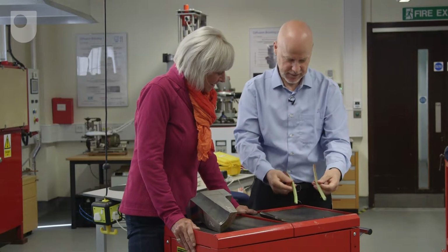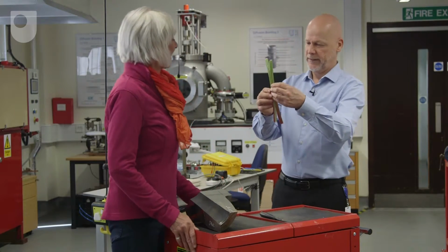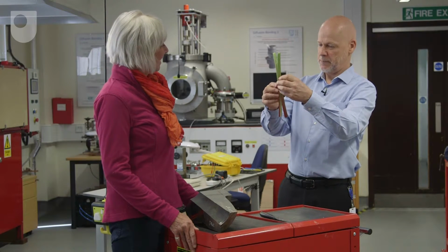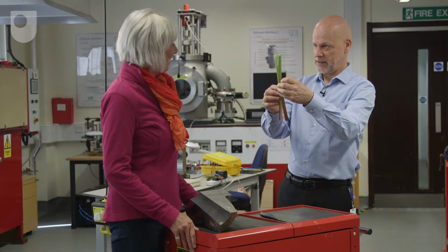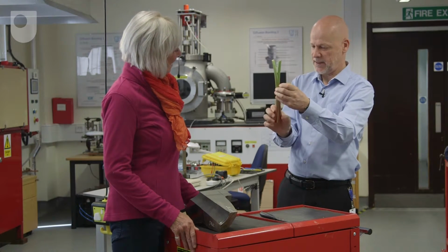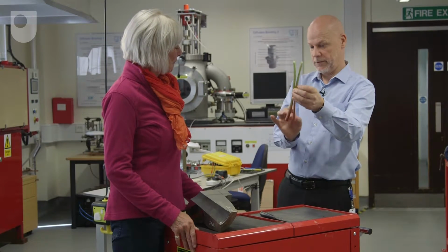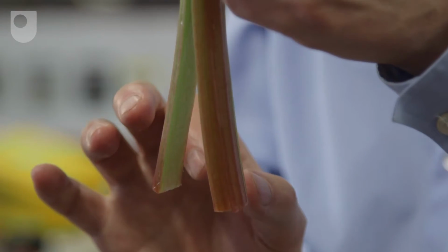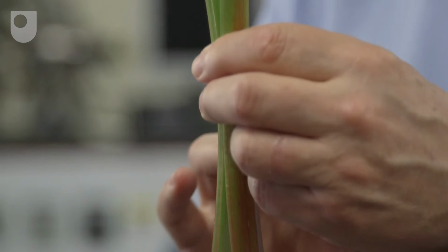And what you can notice is that the cut parts splay out. So they no longer match. And there's a displacement mismatch of the order of 20 to 30 millimeters at the bottom and similar at the top.